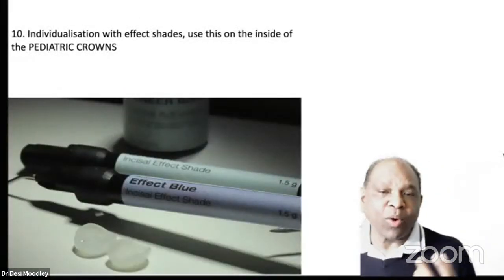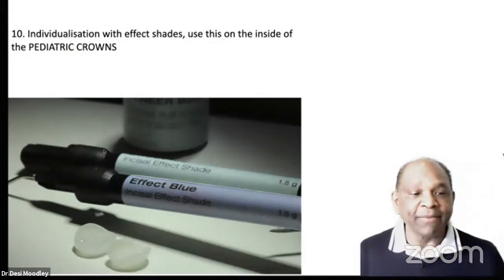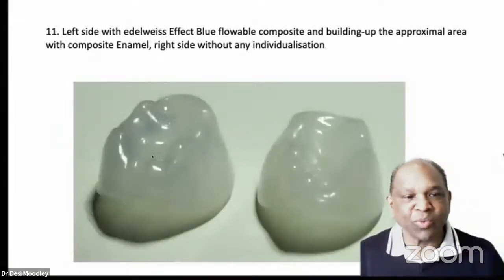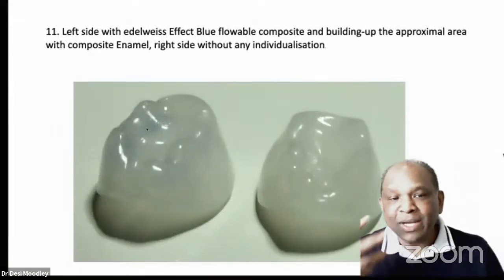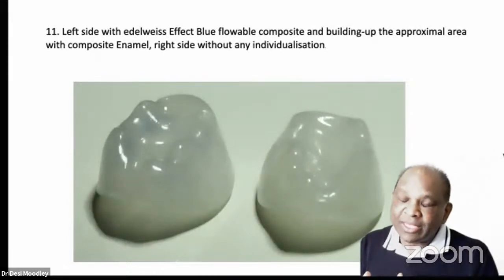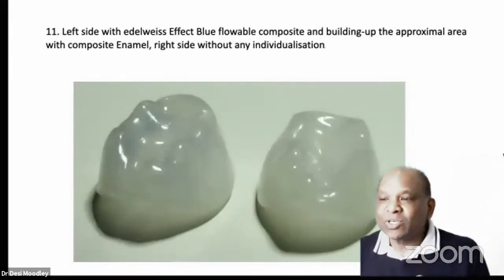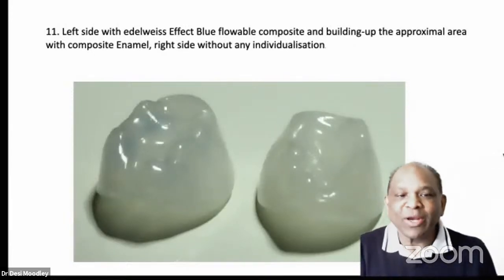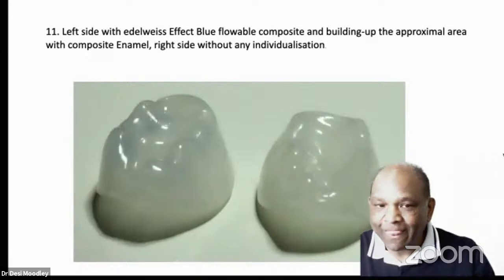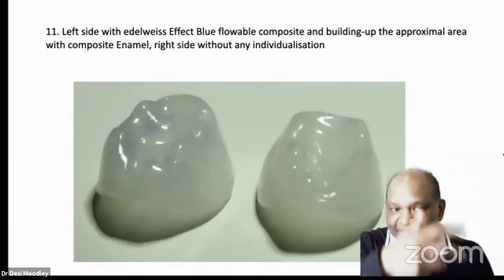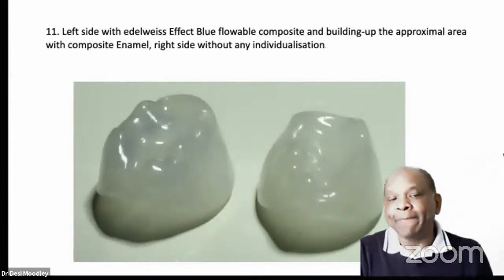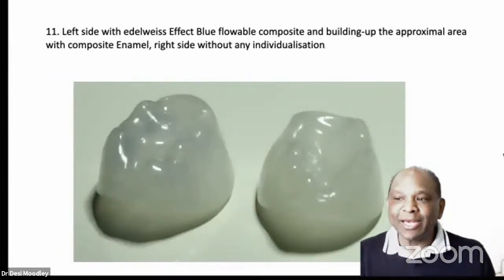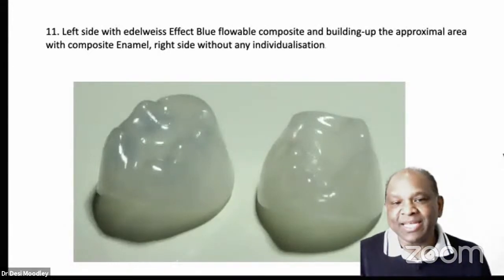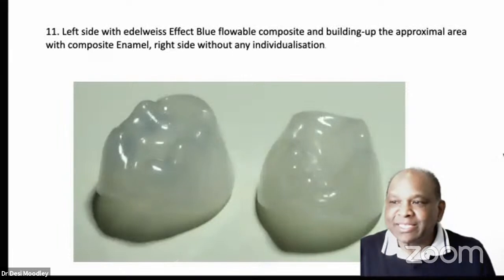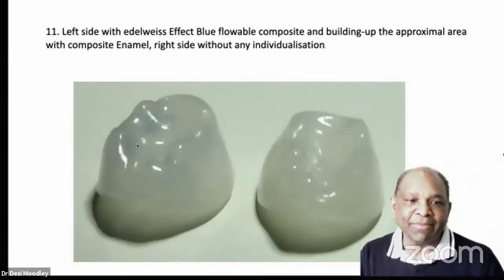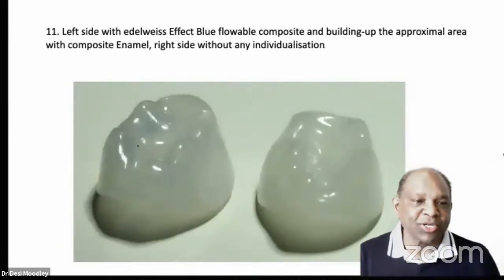You can also add, if you want to, some special effects. For example, if you need to do some halo or whatever effects you want, that's pretty straightforward. You can just tint on the inside, because the Edelweiss crown itself is very translucent. It's almost like natural enamel. So whatever color you put on the inside will shine through. So if the tooth is highly stained or discolored, like the one that I did, I put in a dentine shade composite. So that completely blocks out any discoloration from the inside, and it almost mimics the dentine, and then this will mimic the enamel. So it's almost natural looking.